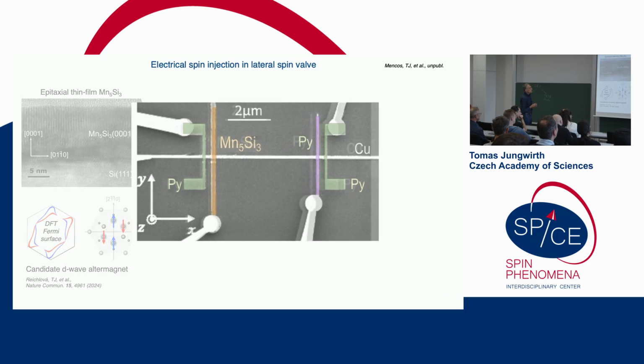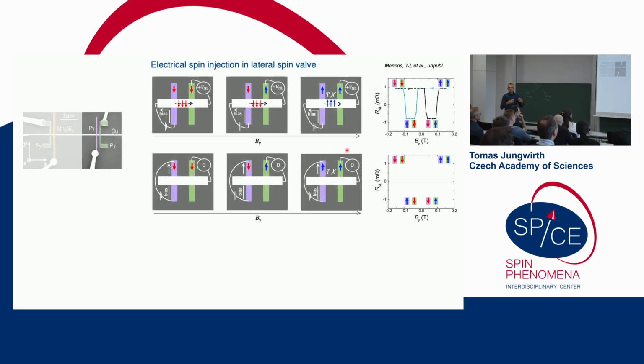So because we have the reference, let me just first go through the experiment on the reference device. This has been done many times, non-local spin detection in this lateral spin valve. The typical geometry in which you inject the spins into this channel is that you apply electrical bias between the ferromagnetic injection electrode and the spin channel here.